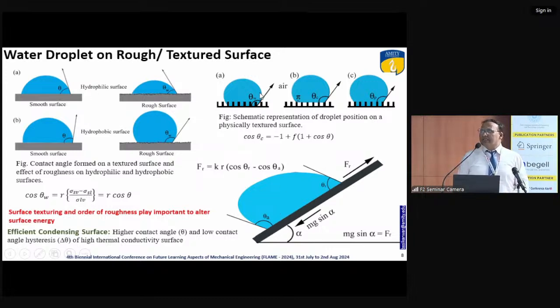And there are three stages of a drop sitting on a microstructured surface. The first stage is complete wetting. The second stage is partial wetting. The third is where the drop sits on air, with no wetting. Because each has advantages and disadvantages, we prepare partial wetting surfaces. For a droplet sitting on a partial wetting surface, the rate of heat transfer through the droplet is very high.